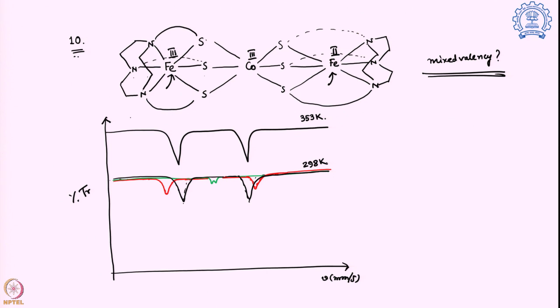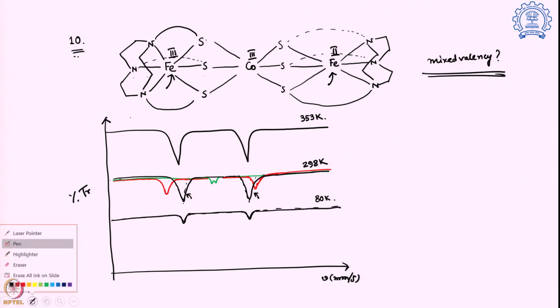Then when we go farther down, what we are able to see is these particular signals actually started shrinking down. This is happening at 80 Kelvin, so quite low temperature, close to the liquid nitrogen boiling point. So this original black trace of the data is now very small. What happened to this red one and the green one? So they actually increase in their component size.